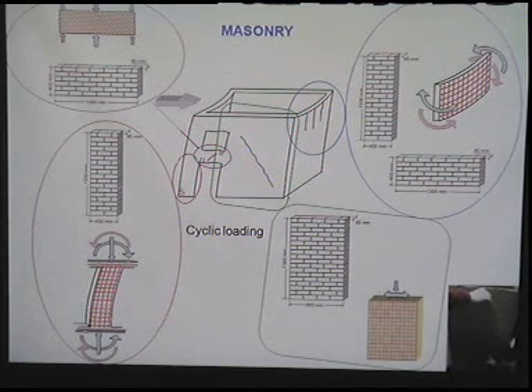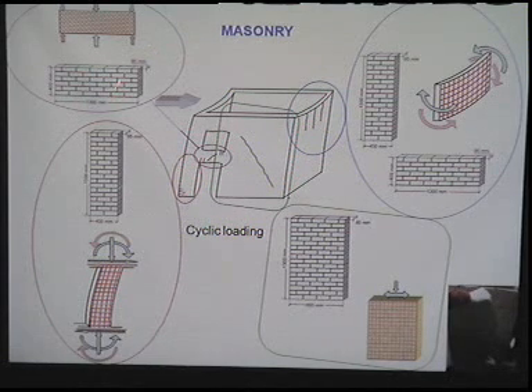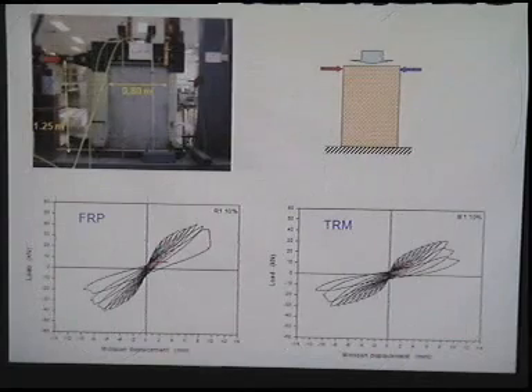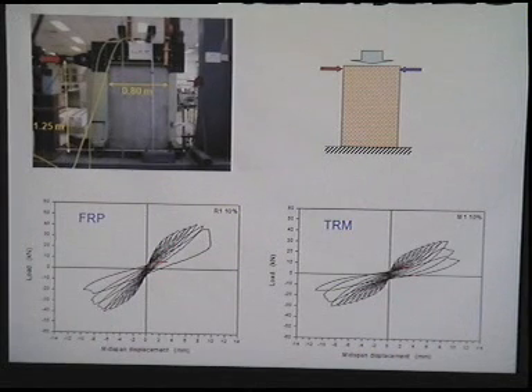So in an attempt to get a better understanding of all those different failure mechanisms, and also with regard to the use of TRMs, we designed several wallettes, relatively small wall-type specimens which we tested in the lab before strengthening and also after strengthening with FRPs or TRMs. I will just give some indicative results to see the comparison between the two systems.